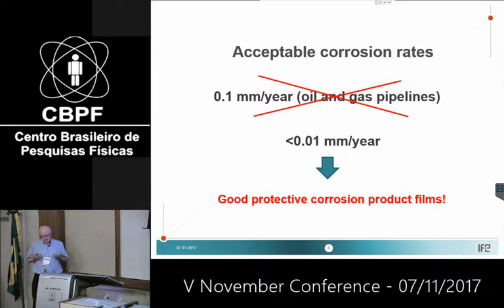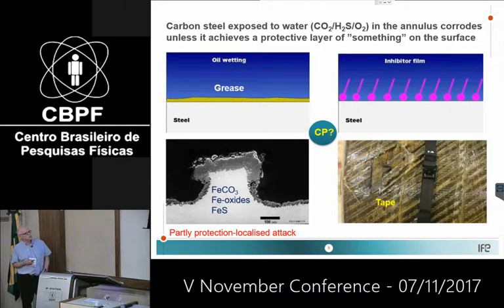And I have been working in oil and gas industry for research for more than 30 years. And we are usually very happy if we can say that the corrosion rate is less than 0.1 millimeter per year. But that would be a disaster in annulus. You need less than 0.01. So you actually need 10 times less corrosion rates than you would be happy with in the pipelines. And that requires very good and reliable protection by the corrosion product films, or whatever that cover the steel. Because in annulus you also have grease, you have tape layers, and that can also cover the steel. But it needs to be covered by something, either this grease or inhibitors that can be leached out of the soft material, or tape layers, or corrosion products. And then if it's coated by corrosion products, you have to be sure that it protects everything.